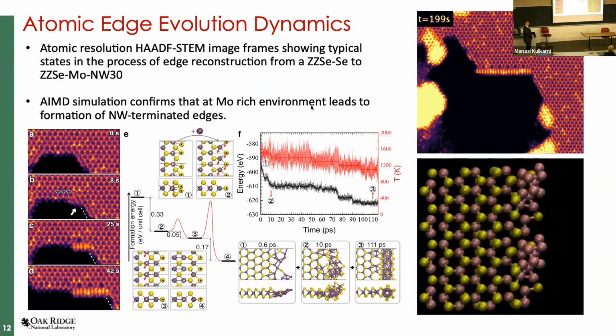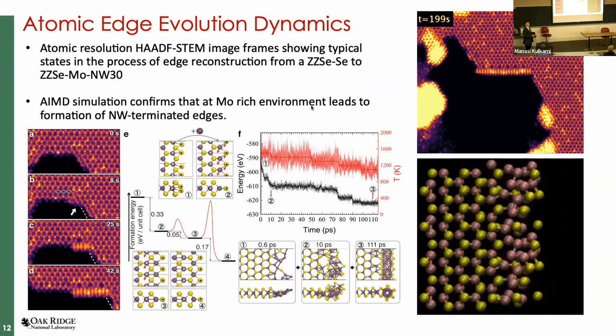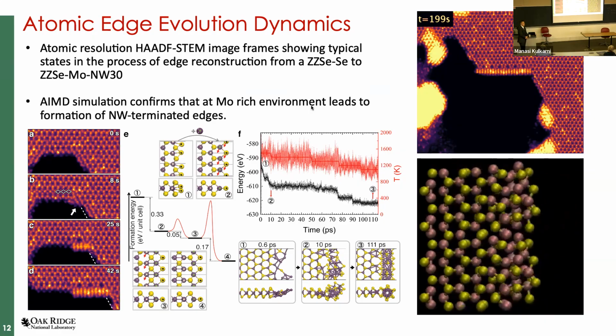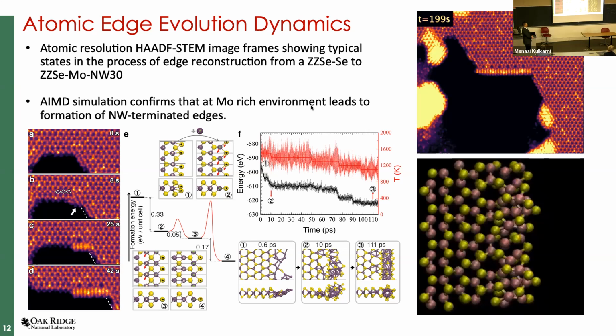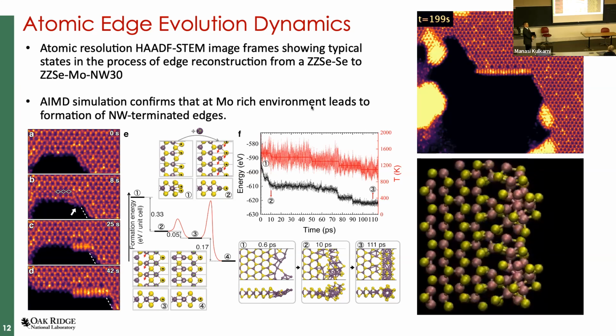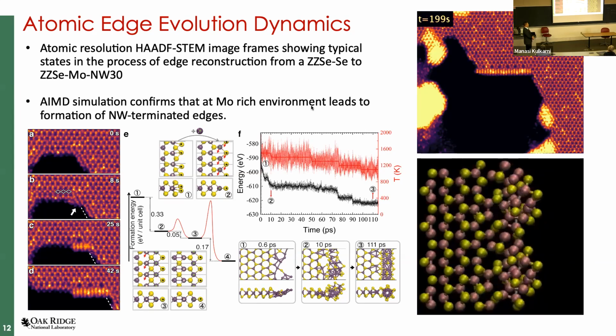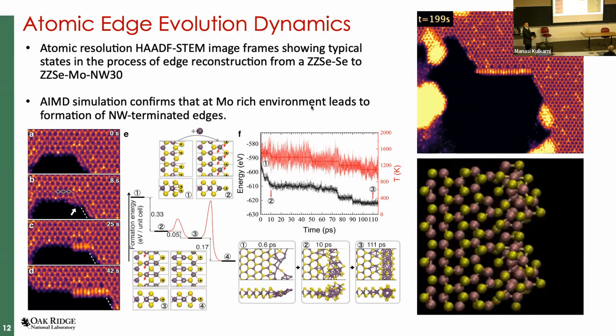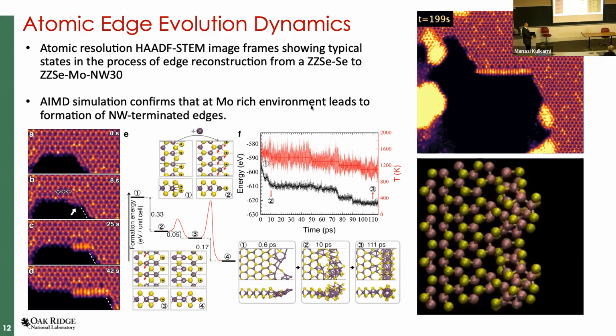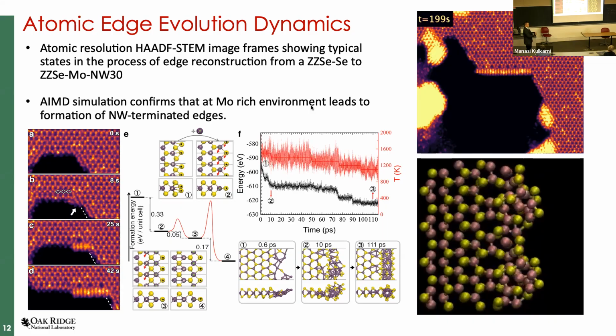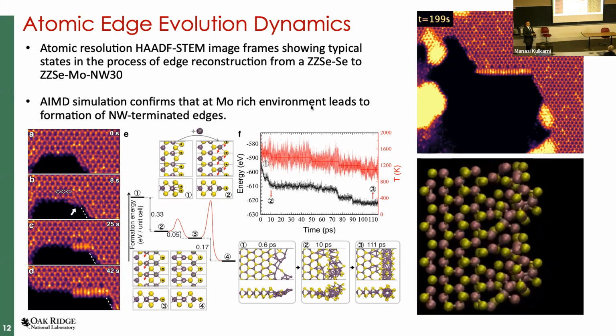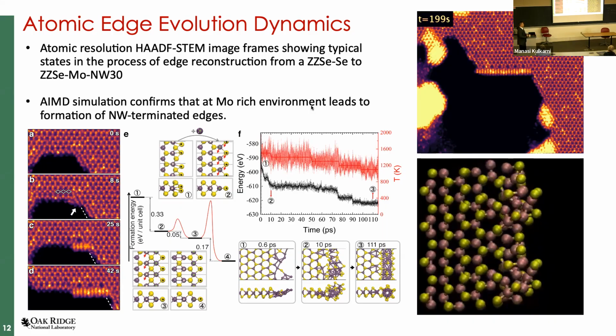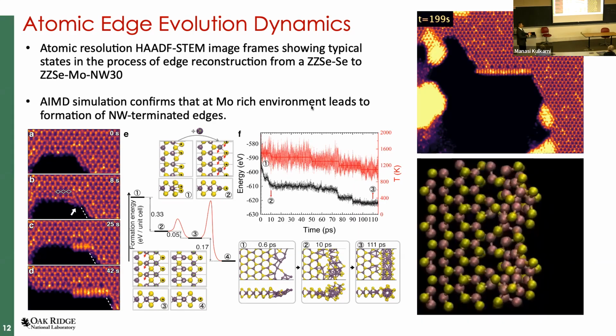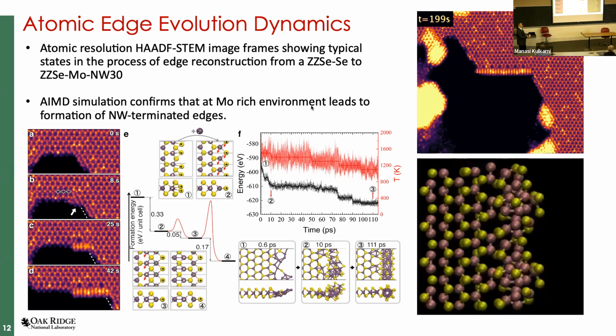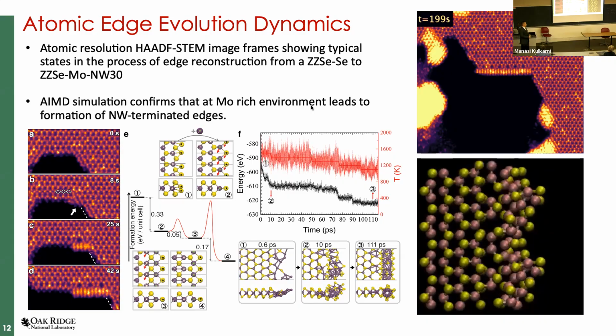Now, there's a drastic change in the time scale that we're doing here. We also turn to folks that do MD simulations. From our STEM images, the time scale is pretty slow. But from MD simulations, we can couple that with our in situ microscopy experiments to get a little more detail about the bond breaking and formation process that forms these reconstructed edges. So these are picoseconds time resolution, and then these are about tens of seconds time resolution.